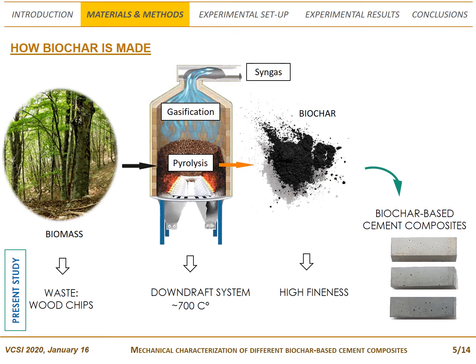The biochar used in this work was produced from virgin wood chips in a downdraft gasifier. The fine particles of biochar, which cannot be applied as a soil improver because of their size, can be used in building materials. Even if several are the benefits of using biochar in cementitious materials, there is not yet an ideal mix design for its use. The results coming from literature are often dissimilar, since biochar comes from different raw materials and from production plants with different characteristics. So, in this experimental campaign, several biochar-based cement composites were analyzed, providing a mechanical characterization in order to verify their possible structural use.